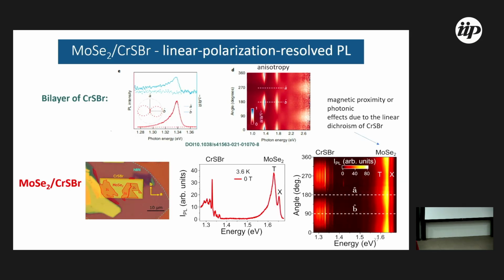There are several unusual results. Another unusual result is about these measurements of anisotropy. CRSBR is the normal one, it emits only in one direction. But MoSe2 is an isotropic material, so it should not change intensity with polarization. When you combine both, if you measure on silicon oxide, it does not change. But if you combine with the magnetic material, we can clearly see that it changed. We tried to understand, and at the beginning Yaroslav Fabian said it's a proximity effect, but after all, we think it is another effect.